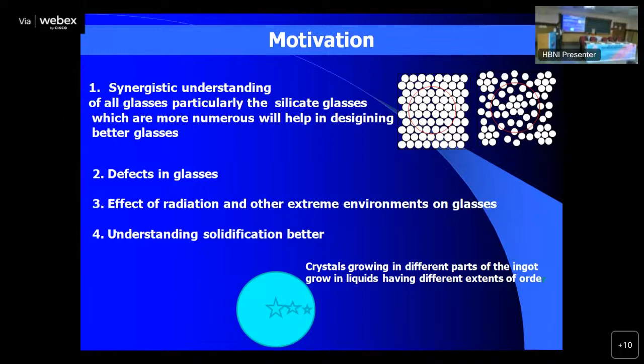2022 was the year of glass as determined by the United Nations. Despite all that, much of the work with glasses, non-metallic glasses, is confined to short-range order. They don't know about medium-range order in glasses. Defects in glasses: do you know about defects in glasses? Well, we don't know, because we don't know the structure. If you don't know the structure, how will you know the defects? Because a defect is a deviation from a known structure. If you know the structure well, you will know what the defects are. So everything is empirical so far, based on trial and error, based on speculation.